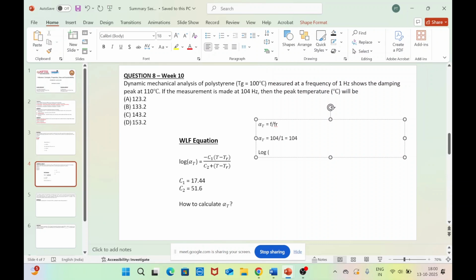So log of 10^4 is equal to minus C1, the value is already given, minus 17.44 times T minus TR. So T is something that we need to calculate, the peak temperature if the measurement is made at 10^4 hertz. So T minus 110 by C2 value, which is given as 51.6. And keep in mind that the values of C1 and C2 are actually constant, so their value will not change. For a particular polymer system, these values are going to remain constant. So T minus TR, T is something that we need to find out, TR is 110.